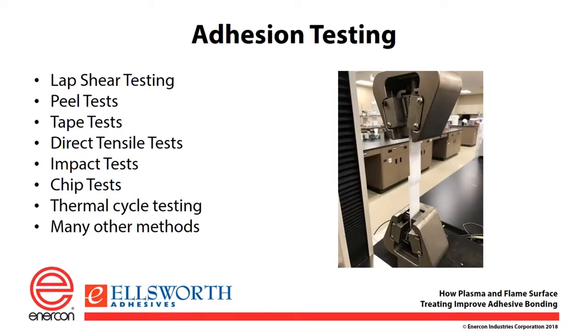There are many different test methods for testing how strong a bond you have. A common one that we run at Resin Lab is lap shear strength. The image on the right shows how lap shear strength is tested. You have two pieces of plastic, in this case high density polyethylene. You overlap a region on the two pieces of plastic. You have adhesive between them, you cure it up, then you put them in the jaws of a universal tester, and you use the universal tester to provide quantitative data for how strong that bond might be.